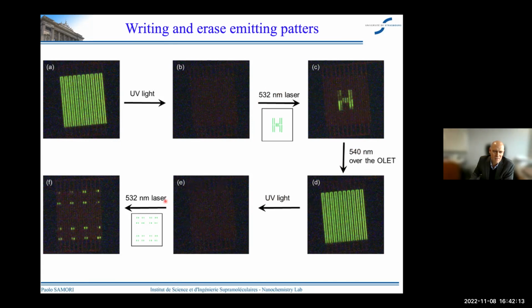And then we can, with the 532 laser, illuminate some specific dots. So you can see that our resolution is extremely high. And as I said, it can reach 1 by 1 square micrometer. So this holds potential for the next generation of display technologies.